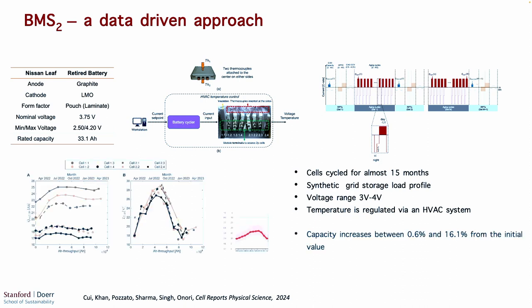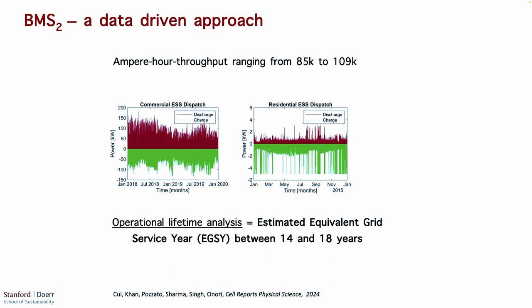And one of the striking results we got is that if you look at the residual capacity of the second life batteries over a period of 15 months or so, we see that the capacity not only doesn't decrease, it actually increases, and the increasing capacity follows the temperature envelope. After these 15 months of operation, which corresponds to around 100,000 ampere-hour throughput, those batteries had enough capacity left. This number corresponds to an estimated equivalent of grid service years between 14 and 18 years, meaning that if those batteries were used in a commercial or residential energy storage system dispatch, they would give you more than a decade of operation.